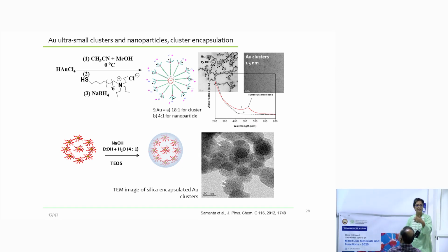Then we got into this fluorescence, and it started glowing very nicely. It was very, very interesting times. And then we did it, and this is what we got. So you can see that, right? So these are the particles. These are the gold clusters which are encapsulated. It is 1.5 to 1.7 nanometer, and we make this after calcination at around 350 degrees. So at 350, this is what we got.